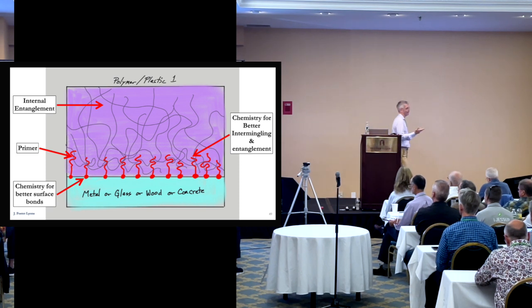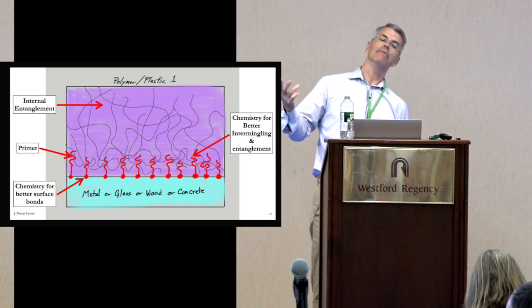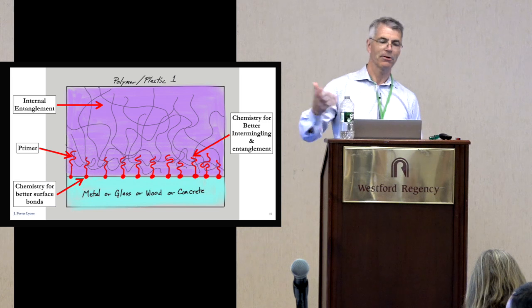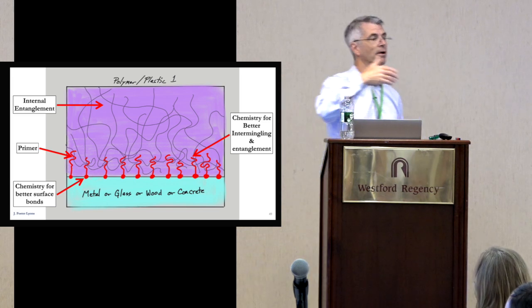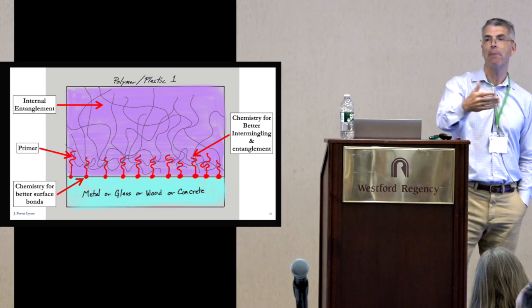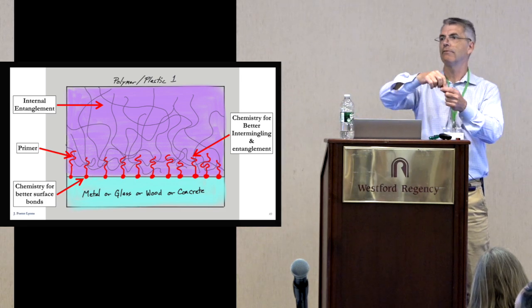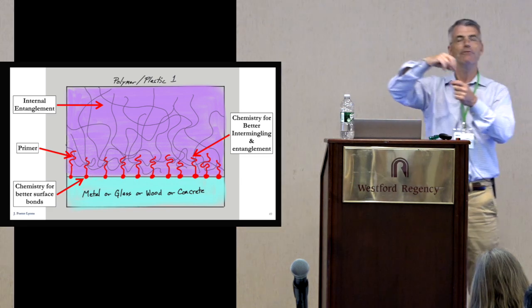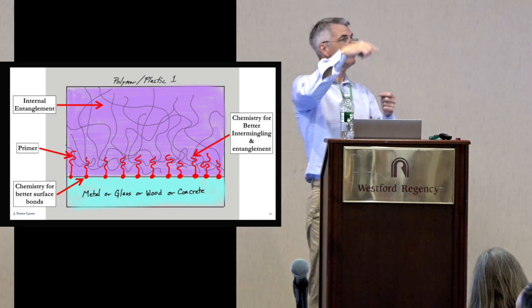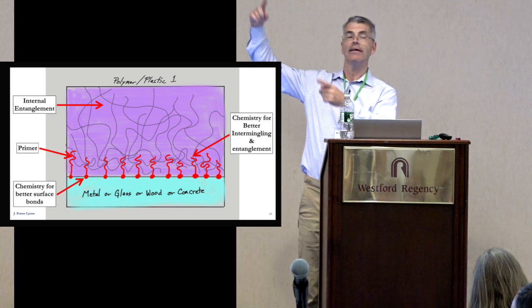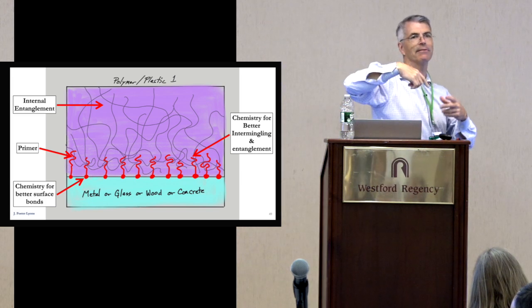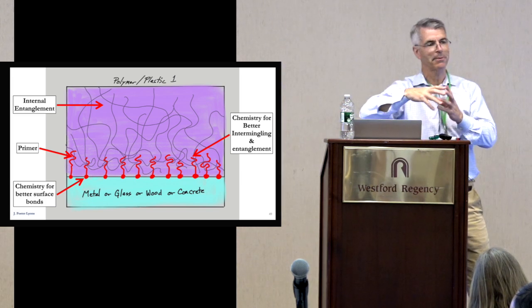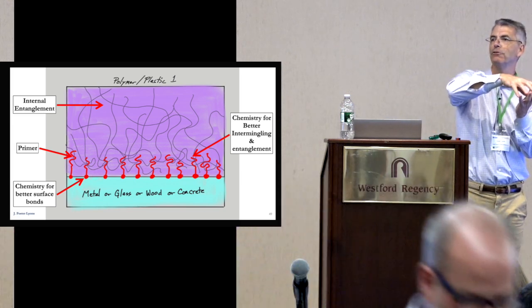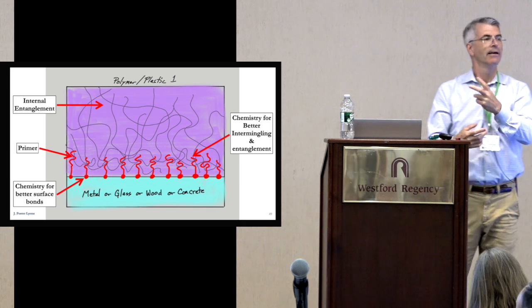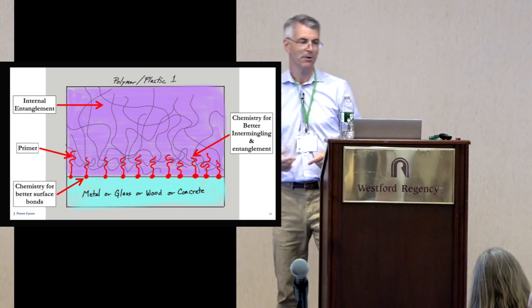So primers, okay? Primers are a thing. A lot of manufacturers require them for various materials. Well, what's going on? It depends on the material that you're bonding to. It turns out some primers are better than the primary adhesive for developing surface energy bonds to whatever surface you're trying to bond to. And there's a little tail of polymer off those individual surface energy bonds from whatever primer you're using. And that tail mixes very well with the adhesive you're going to put on top of it. So the biggest thing the primer is doing for you, probably not the only thing, is allowing you to make a good surface energy bond, and then it's intermingling and entangling very well with the adhesive you're actually going to use, okay?